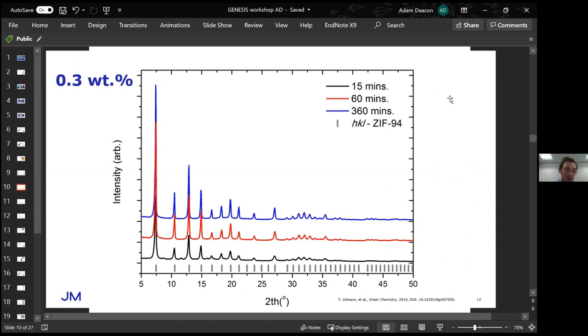We set out by looking at a systematic way to improve the synthesis. We did a number of small-scale experiments at five gram scale. When we produce this material at low weight percents, at low reaction times we see the presence of an impurity. This impurity is identified as ZIF-94, but if we continue the synthesis this impurity disappears and eventually we produce a phase pure material.